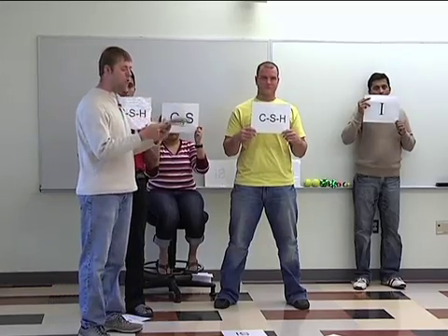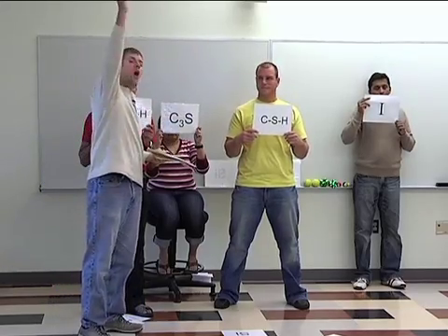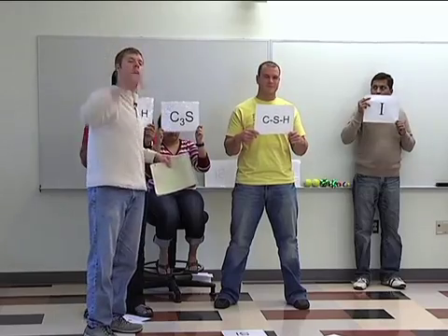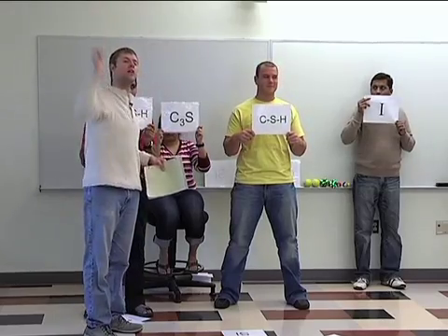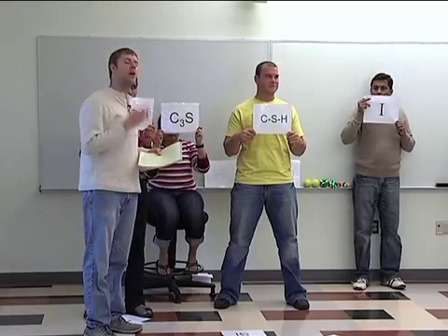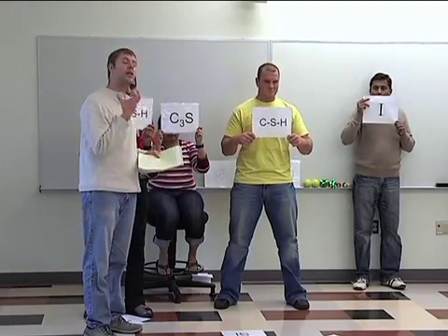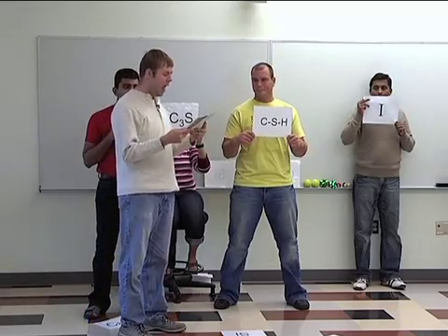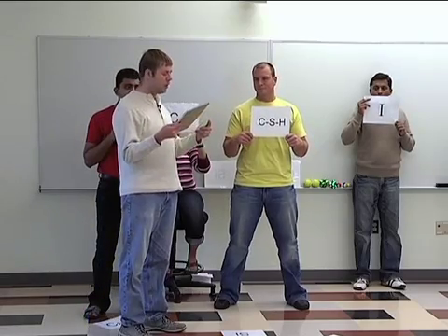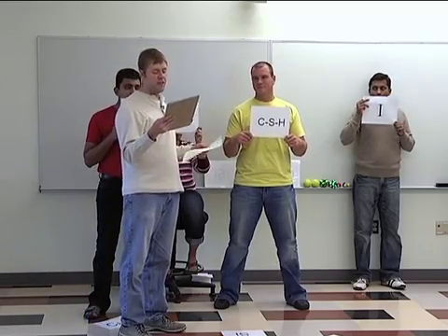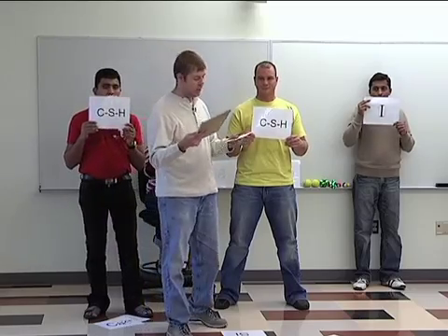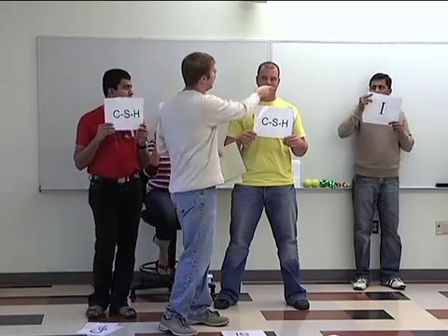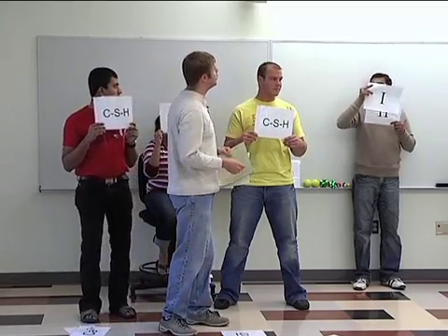Our heat release goes down. A few water molecules make it through. Our ions are going up and up in solution — we get more calcium ions going up. The silica is being consumed initially right with the CSH reaction and very little heat is given off. And this begins our induction period.